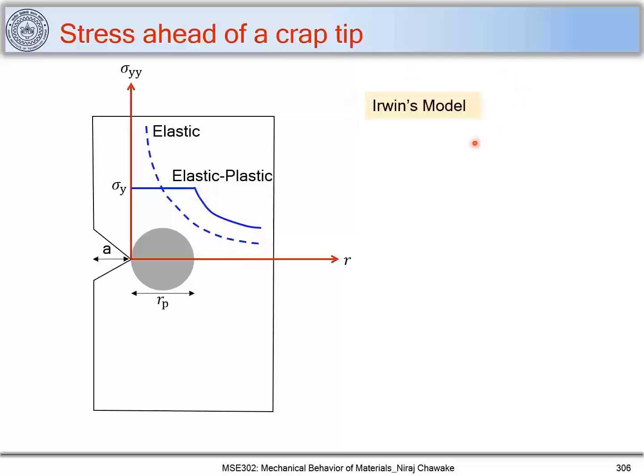Irwin has described this kind of elastic plastic material using a model, and he considered this radius to be a effective, where a effective is nothing but this crack length a plus Rp, which is the diameter of this plastic zone. So we have a effective, which is considered to be a plus Rp, and this Rp can be found out by using this radius R1, and this Rp is almost equivalent to twice R1.